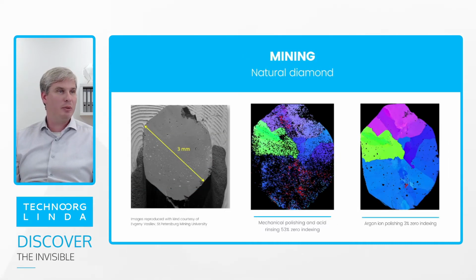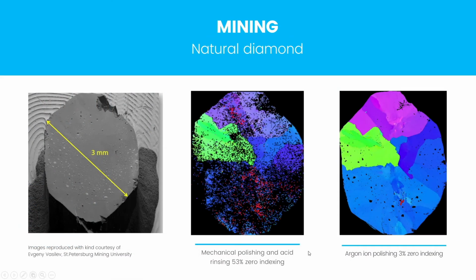From the mining industry, we have a beautiful sample here. It's a natural diamond. It's obviously very hard to prepare mechanically. Here you see first they tried to use a mechanical preparation, the mechanical polishing, including the finest steps of that approach. And then they tried also a chemical etching, but combining those techniques, that was the final result, what they could achieve. About half of the points were just not good enough for indexation. So that's a very poor result.